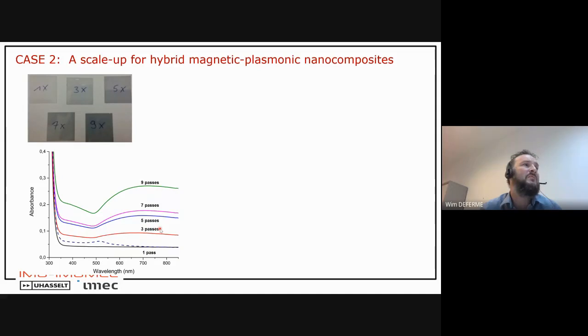And that means that these gold nanoparticles will cluster together, and you see this change in what you expect as the absorption peak of your gold nanoparticles, 5 to 10 nanometers, around 530 nanometers. You see that you get a redshift, and that means that we have clustering of our nanoparticles. So that's something that we have to optimize by playing with, let's say, the composition or the way the nanoparticles are synthesized.